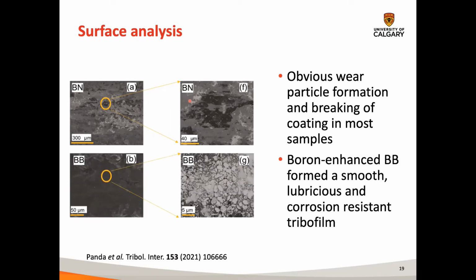And if you compare this to the boron enhanced top layer, you don't see this removal of the top layer. You can't see into the substrate, and you see this sort of plate formation in the wear track itself. And so this is what's really providing this lubricious friction coefficient that we measured in our experiments.